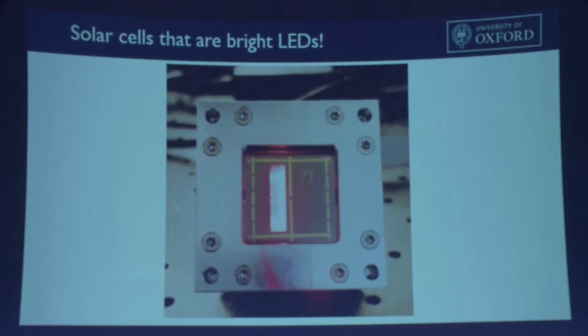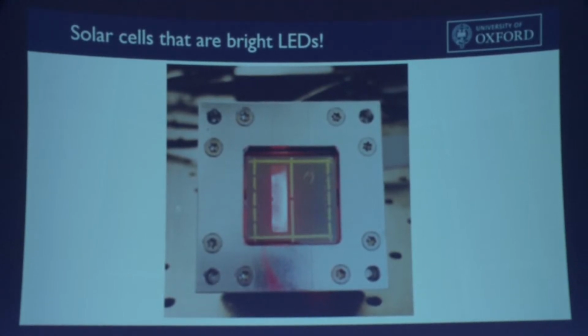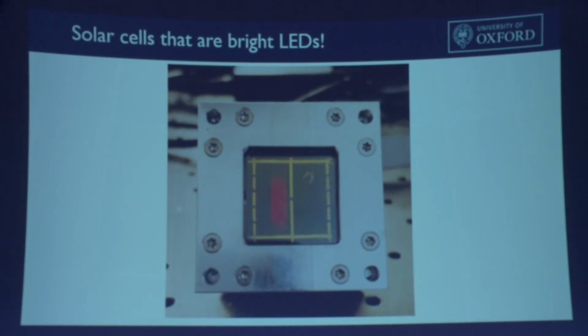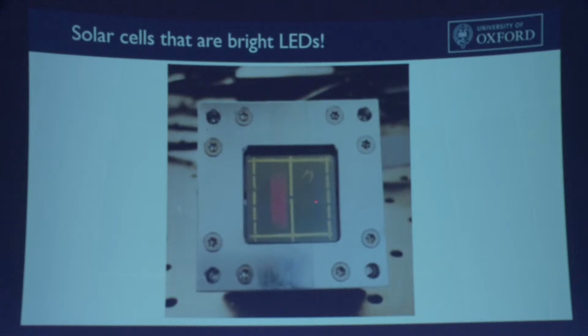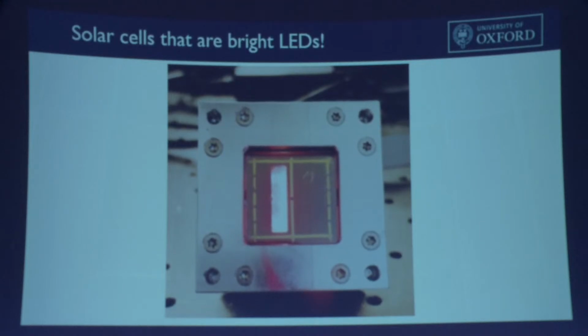These solar cells actually emit light pretty strongly. Because we've tuned the band gap to absorb visible light, you can now see the light that's emitted. So this is a solar cell where we don't shine light on it and get current out, but we drive current in and we get light out, and we can see it with our naked eye very clearly. In fact, there's a whole analogous technology, very similar to OLEDs, of perovskite light-emitting diodes, where these device stacks are engineered slightly differently to emit light for displays.